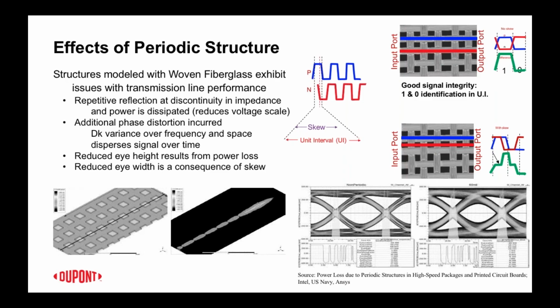So some of the other modeling that we leveraged in presenting our materials against conventional laminate types is some work that was done by Intel, US Navy, and ANSYS, and they modeled the effects of a periodic structure on transmission loss, transmission line performance. What they show, and this is irrespective of skew, which we'll get to a little bit later, is that even when transmission lines are on a board built on a bias relative to an orthogonal orientation to the panel, there's still going to be the case of the transmission lines crossing over individual yarns.